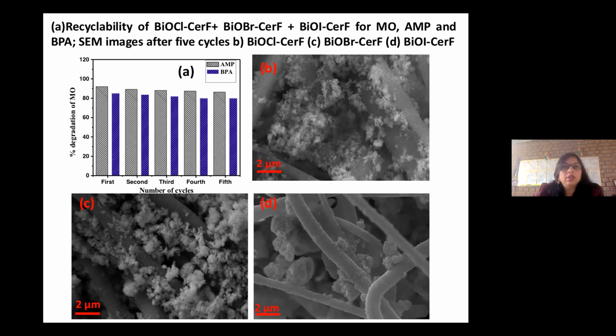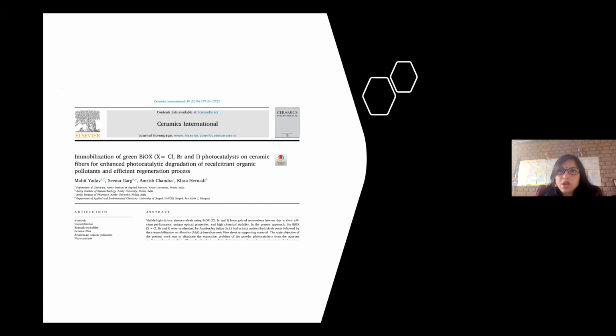These are the recyclability studies. Almost the same results we found in the cases. Here are the SEM images of the used material; almost the same SEM images we found after using the material. So this paper was published in Ceramics International.